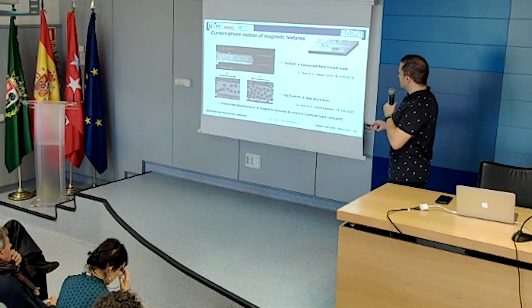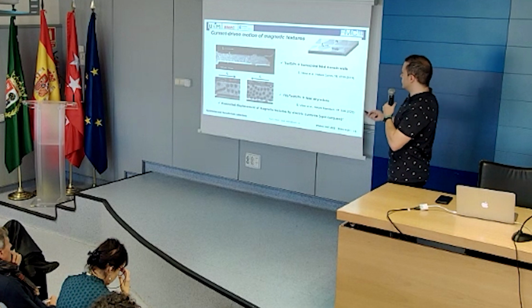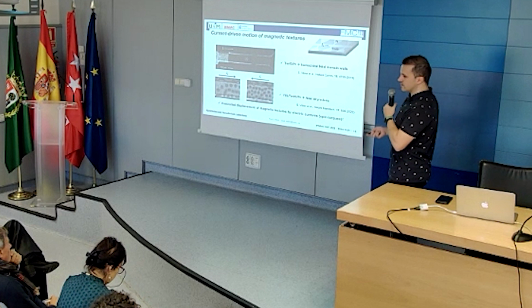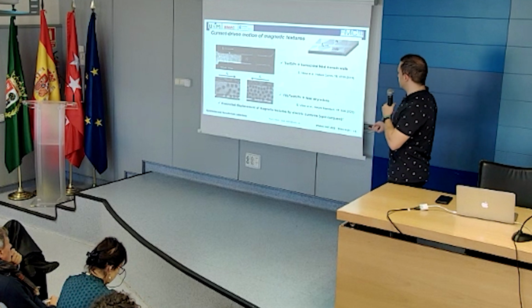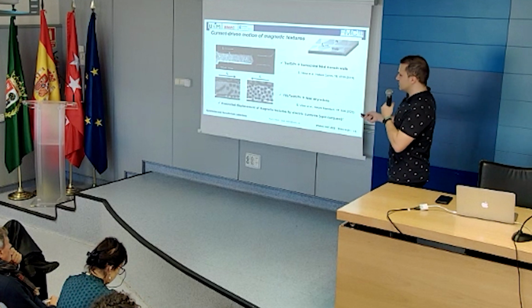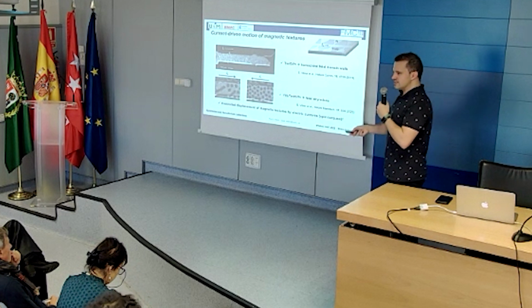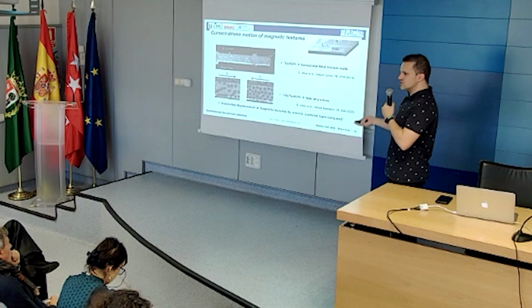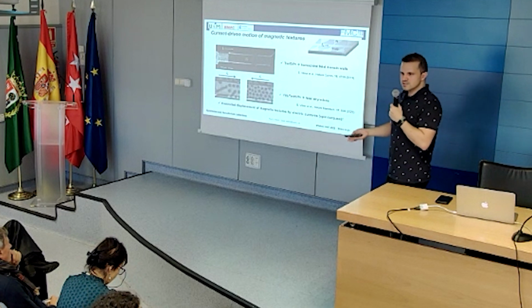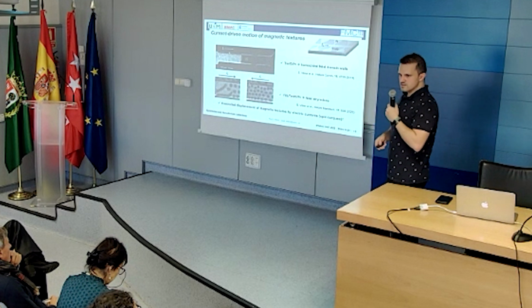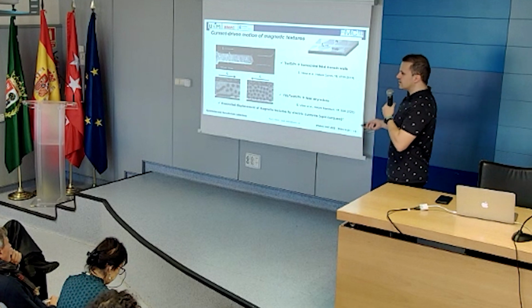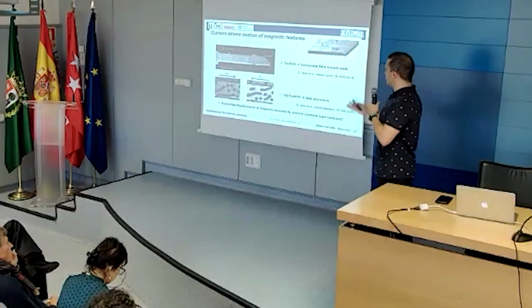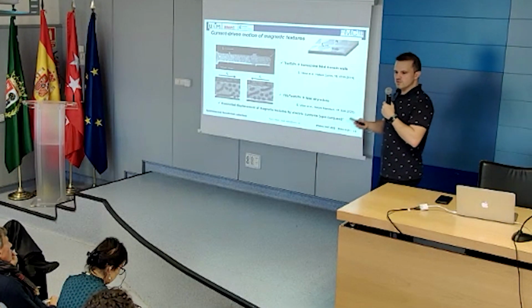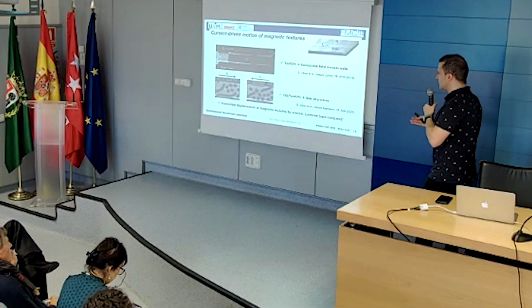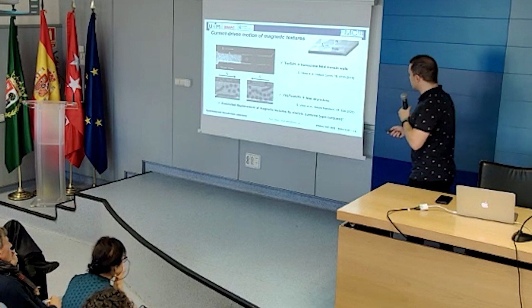Then we went a little bit further and we could also stabilize skyrmions in magnetic insulator layers. You have to think that these are non-conducting magnetic layers, and we can drive them, and the velocities that you get are similar to the metallic ones. The idea is that these materials, because they are epitaxial and have very low damping and so on, could even have the potential to surpass the current metallic technology.